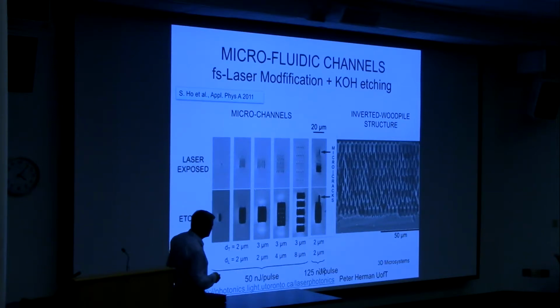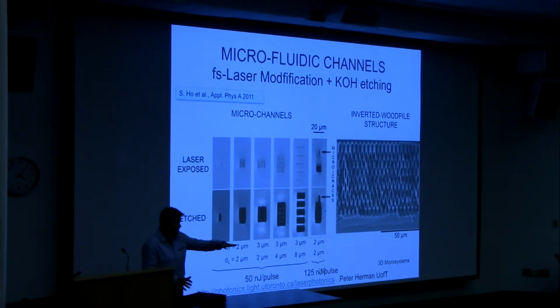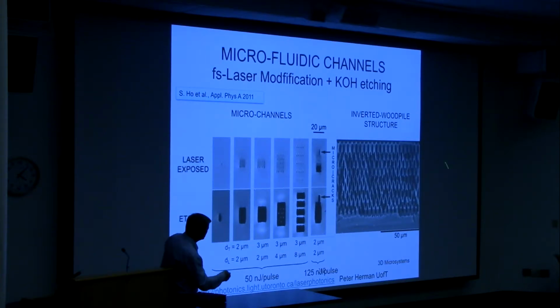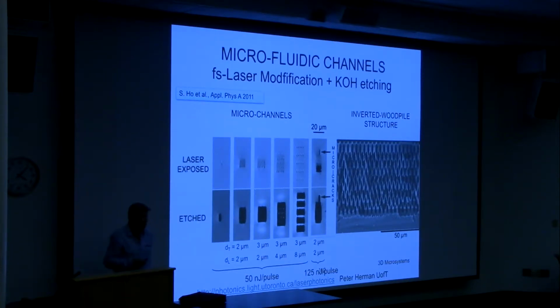And I just want to say these are laser scans that are layers of, let's say, log patterns this way, then this way, and this way. The chemical has opened those up, so it's inverted this, and you're left with this almost impossible to make form of glass. These little membranes here are just 2 microns big, and it's very intricate. This is formed over 100 by about 80 microns, and it's a channel along the surface. So this might be useful as a chromatography type structure. All silica, very biocompatible, that really would be hard to make any other way.